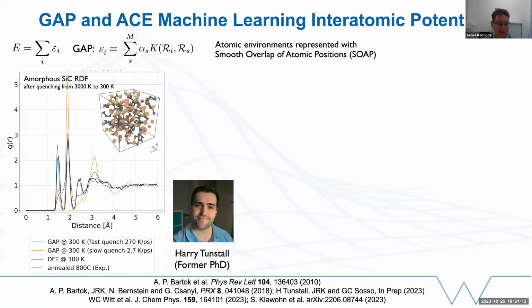To show one relatively recent result from my group using this approach, this is work by Harry Tunstall, who's a PhD student who finished a few months ago, looking again at silicon carbide, but now we're interested in the amorphous phase of silicon carbide. What we want to reproduce is experimental observations of the radial distribution function, the structure of the amorphous phase, essentially. You can see the experiment as the black dashed line here. And what we were able to do is move towards an improved description of that.